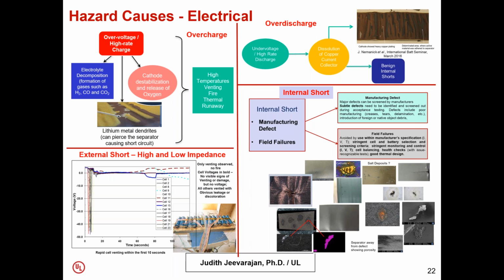Dissolution of copper from the copper current collector happens. And if you do an extreme over discharge and it goes into negative voltages for prolonged periods, you can actually dissolve copper and deposit it on the cathode, anode, and separator. The electrochemical system now becomes an electrical wire, and you have a short inside the cell, but it's a benign internal short. And the cell dies; you cannot charge the cell anymore.